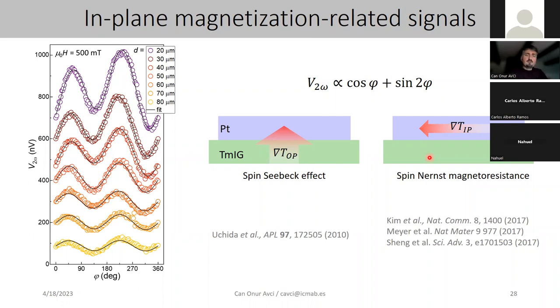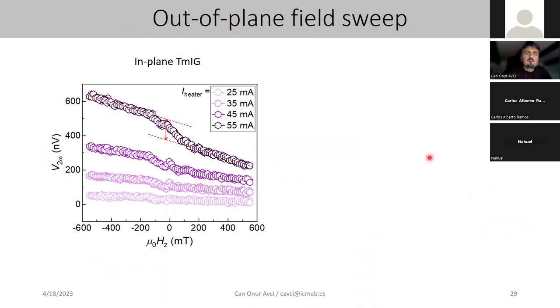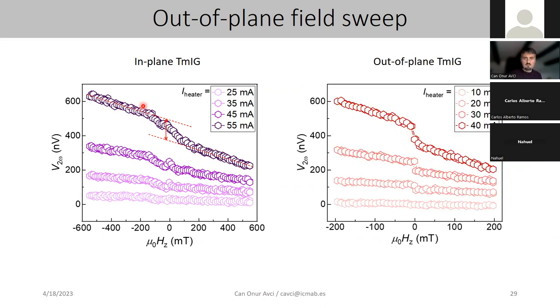The interesting observation came out when we did an out-of-plane measurement, because we saw that there was also a signal occurring in the out-of-plane field sweep. This sample was magnetized in-plane, so therefore you don't see this very clearly. We said, okay, there is something here, but we don't understand it very well. So let's make a perpendicularly magnetized sample. In that case it was more clear.